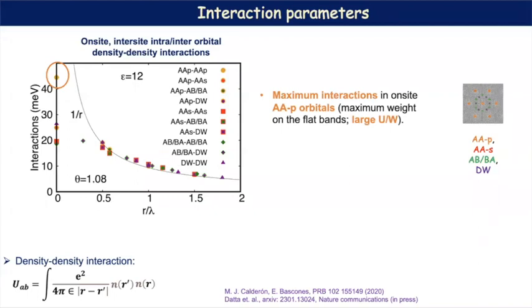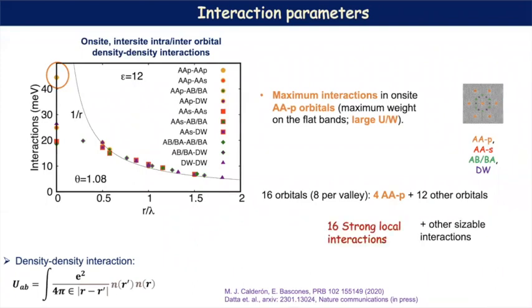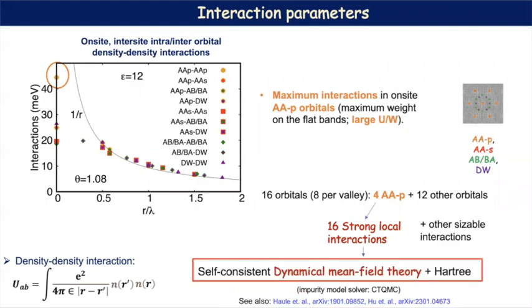Because these orbitals are mostly in the flat band, they have a large ratio of this interaction over the bandwidth. We have 4 of them in total, and so we have 16 strong local interactions. And we have other interactions, and so we treat these 16 interactions within dynamical mean field theory. The other interactions are also not negligible, but they're not as high as these, so we treat them within the Hartree approximation, and we have a self-consistency between the two techniques.